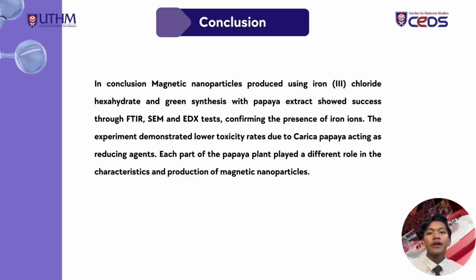In conclusion, the magnetic nanoparticles that use iron 3 chloride hexahydrate through the process of green synthesis with the extract of papaya leaves, peels, and branch have indeed come to success. This is stated because of results from FTIR, SEM, and EDX tests that stated that the ions of Fe, which are iron, indeed exist in the nanoparticles tested. This shows that the nanoparticles tested indeed contain magnetic force because of the Fe ions in the nanoparticles.